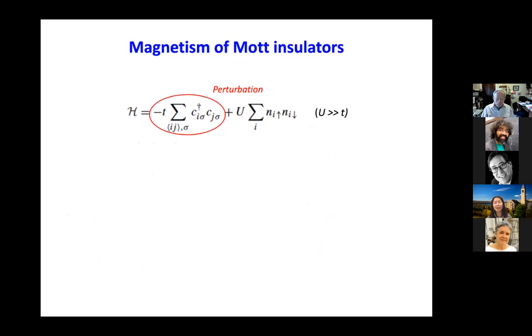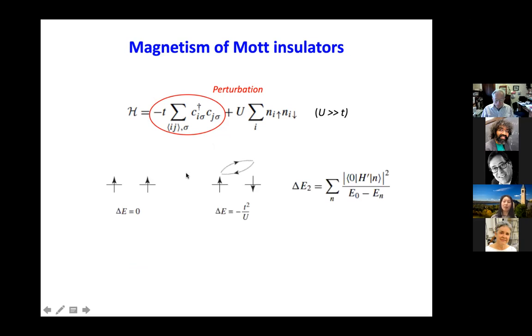And this antiferromagnetic interaction between localized moments is very consistent with the Hubbard model when you have strong interaction. So let's just look at those two terms. If U is much bigger than T, you can treat T as a small perturbation, right? Therefore, it is possible to have an exchange, in this case a superexchange, for one spin to hop over and hop back. And that's the second order perturbation. But if the two spins on the neighboring sites have the same alignment, then this process is forbidden. And only when they are anti-aligned do you get a contribution.